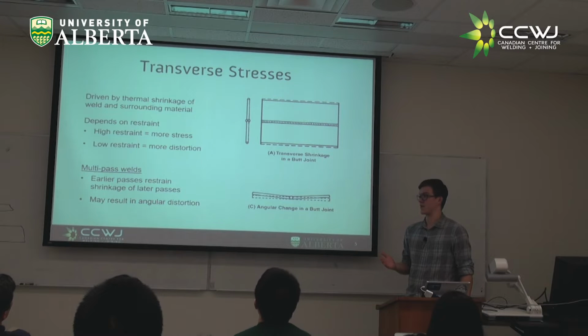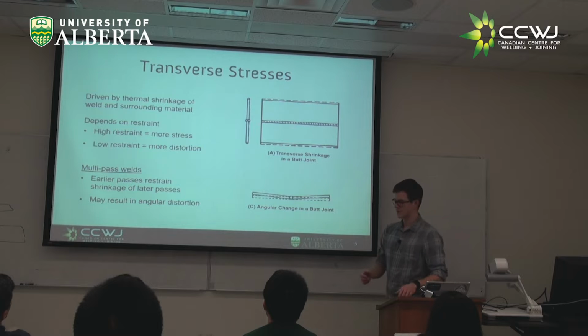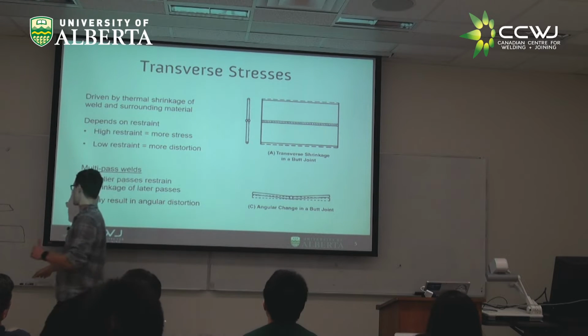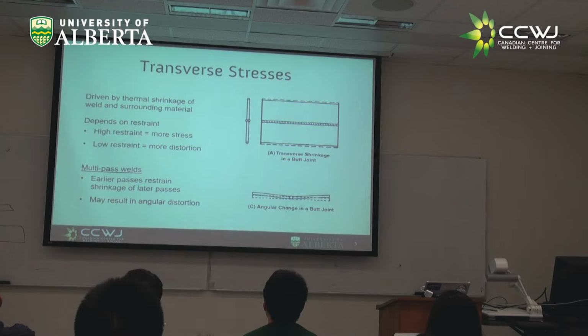And in a multi-pass weld, it's not just the restraint of your plate, but it's the restraint of the earlier passes. So if you look at the case we had here, where we have a first pass, say a root pass, that gets put in here. Now for each subsequent pass, when that wants to expand and pull back together, this pass is restraining it. So as we move up, each of these passes gets more highly restrained, and the stresses are not then consistent throughout the thickness. And an uneven stress distribution through the thickness is what gives us those distortions.